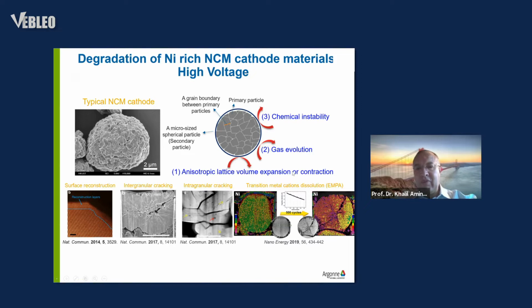Again, at 4.3 volt, you can get better stability, but at high voltage, basically, you have some additional phenomena. One of them is the cracking, as you can see. Another one is the release of oxygen that causes reconstruction or phase transition at the surface from a layered phase to spinel. So these things are very difficult to overcome when you operate at high voltage. So what you really need is a very uniform conformal coating that covers the whole particle inside and outside. And you cannot do that by a simple co-precipitation of metal oxide on the surface of the active material or the secondary particle of the active material.